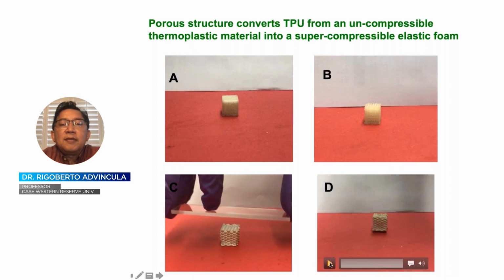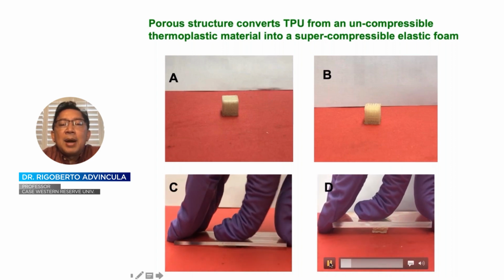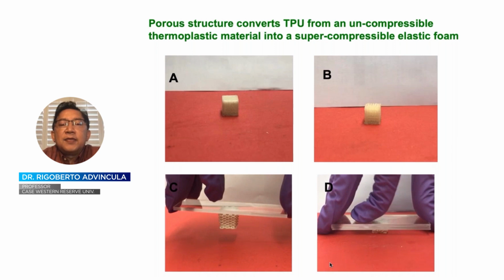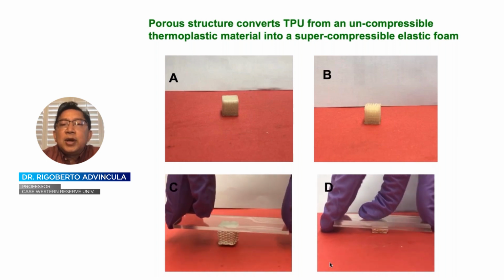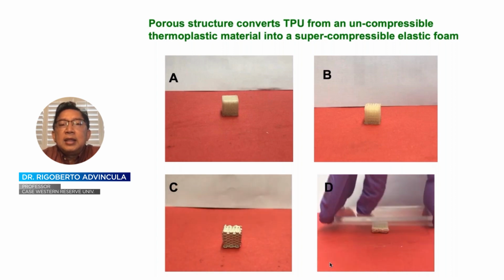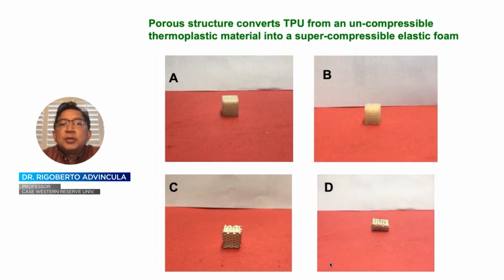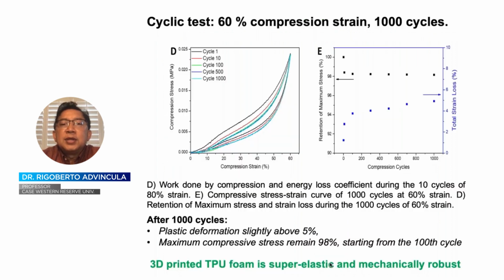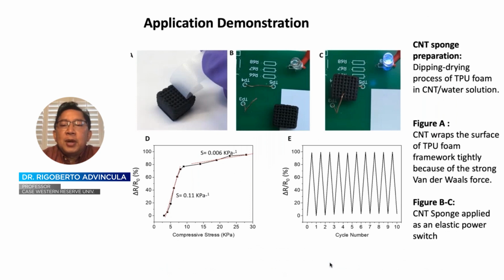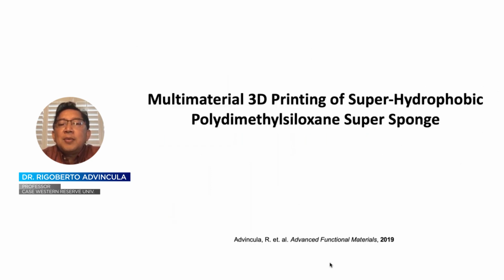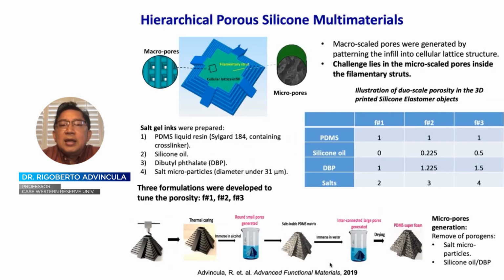And again, depending on the loading of clay and the amount or design of the object, we can change their compressibility. So what this means is we are able to use 3D printing and the material property itself to elicit a new response. And in fact, these materials are classified as super elastic materials with up to 1,000 cycles in repeatability with 60% compression retention. Okay, and we in fact use this object practically as a switch to light LED diodes with an impregnated carbon black surface. So what I'm going to show you are some work that we have done as an extension of